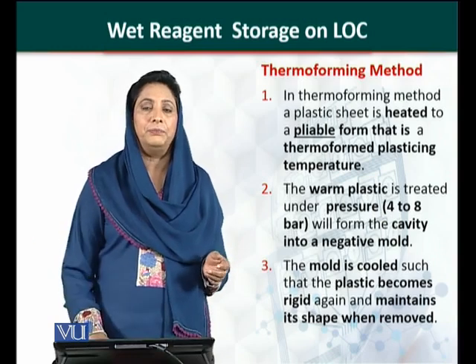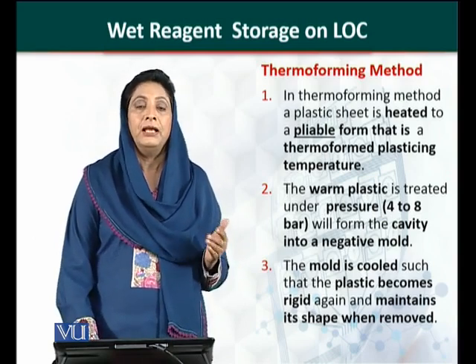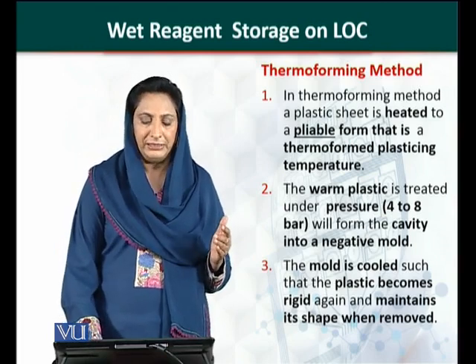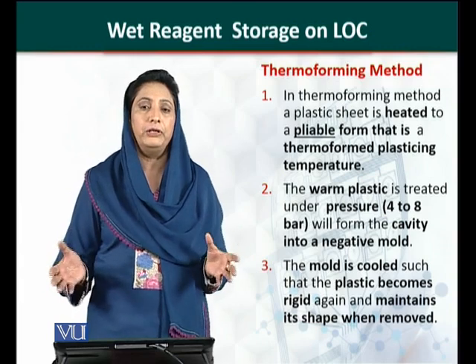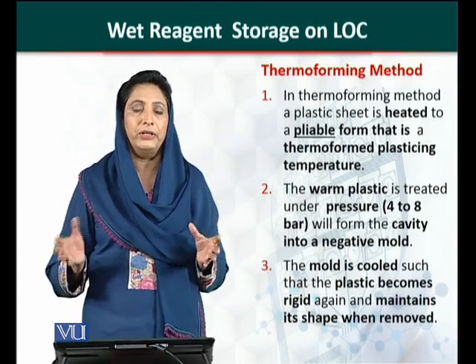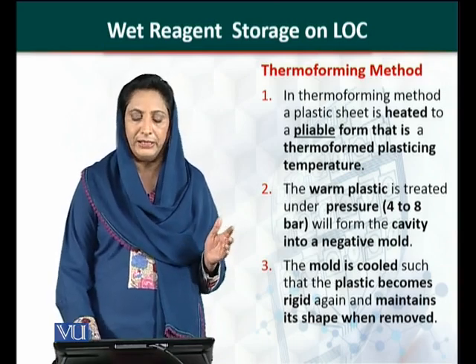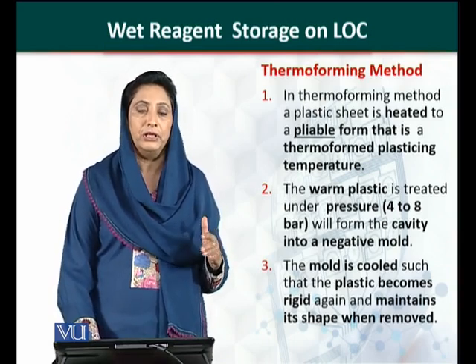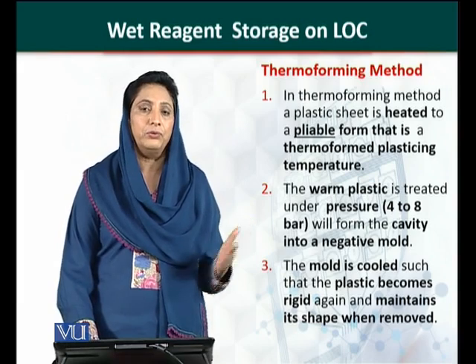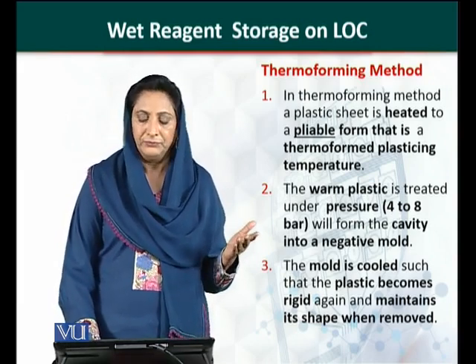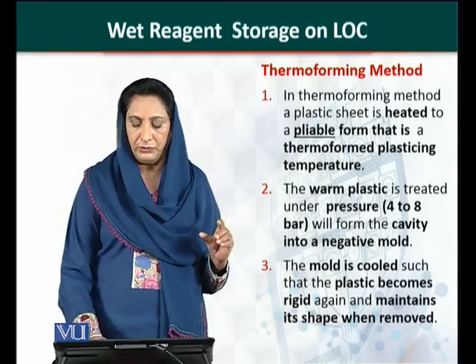The next type of method is the thermo forming method. In this method, we use plastics or plastic polymers. The plastic is heated to the point that it becomes pliable — a state where the plastic is softened and can be molded or converted into the initial form we want. After that, this warm plastic is placed under a certain pressure of up to four to eight bar, and a cavity is formed into a negative mold. The plastic should be in melted pliable form and under pressure; when the mold is cooled, the plastic becomes rigid and we get the proper shape of the micro dispenser.